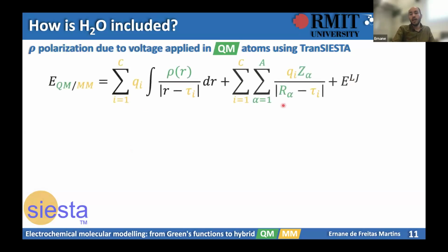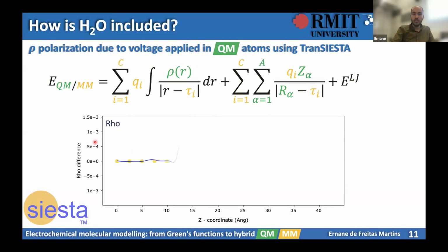First of all, if we look at this expression, here we have the electronic density from the quantum part. If I make a plot, just an illustrative plot of this electronic density, taking the difference between a case without a voltage and with a voltage, we can clearly see charge accumulation in one of the extremes and charge depletion in the other extreme. What does that mean? The effect of the voltage is already present in this term, and we interact this with classical charge, so the classical atoms will respond to this. But we need to account for this voltage in the classical atoms as well.